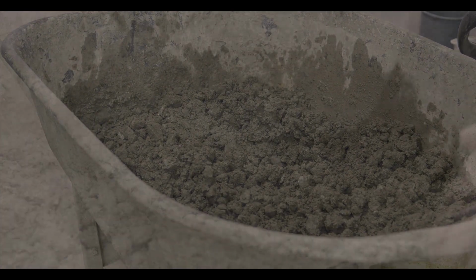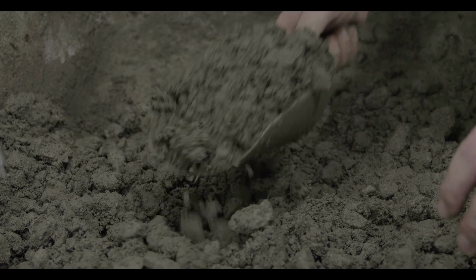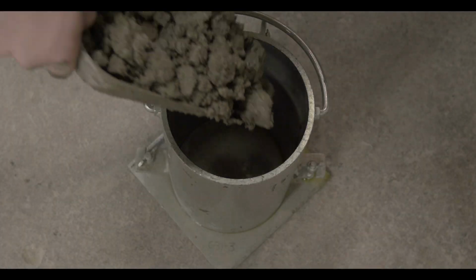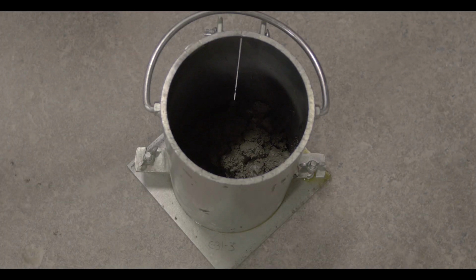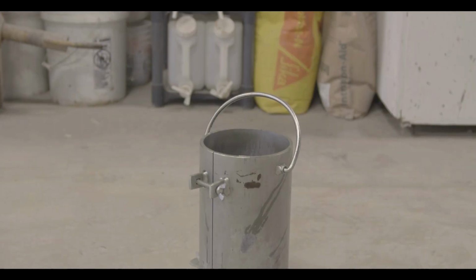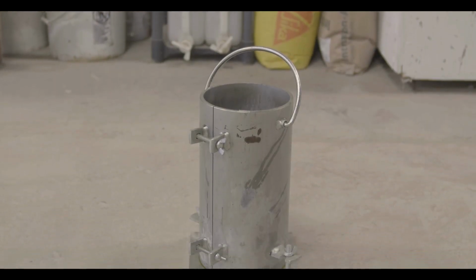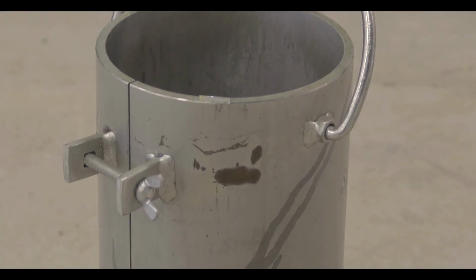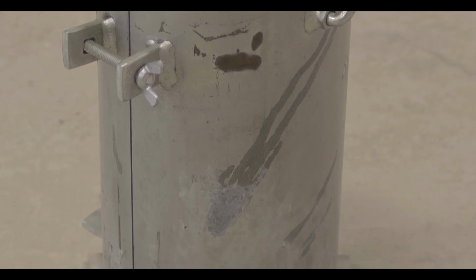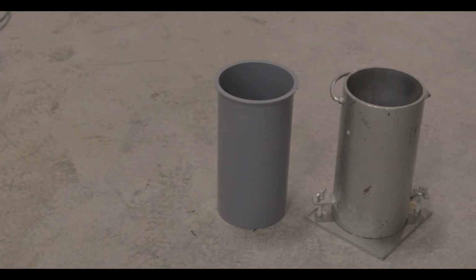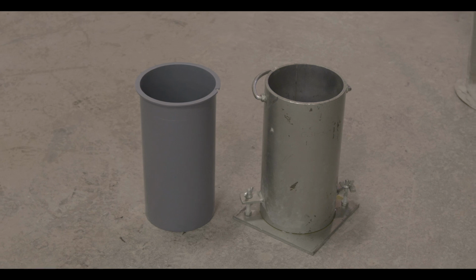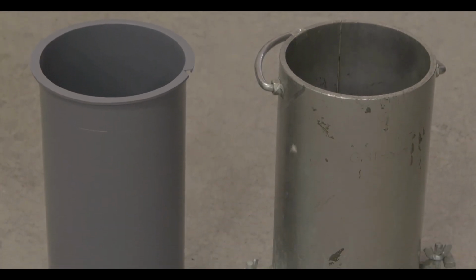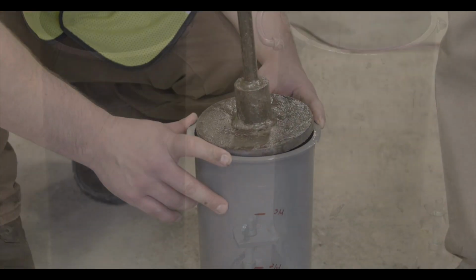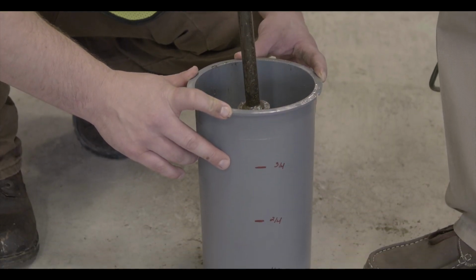using a vibrating hammer. The method is used instead of rodding or internal vibration, which cannot properly consolidate concrete of this consistency. The equipment needed for this test method includes a Type A reusable mold conforming to ASTM C470. It shall be 6 inches in diameter and 12 inches in height. Or a Type B single-use plastic cylinder mold may be used in place of the reusable mold. It shall also conform to ASTM C470 and be 6 inches in diameter and 12 inches in height.